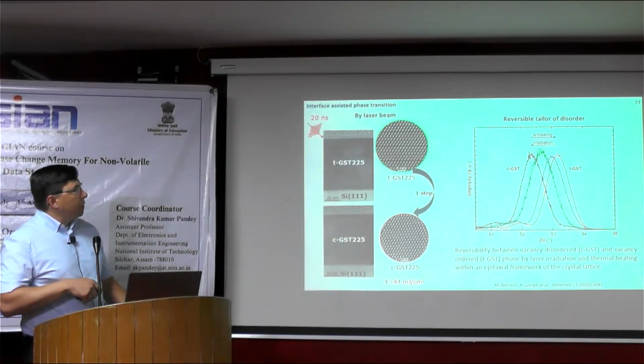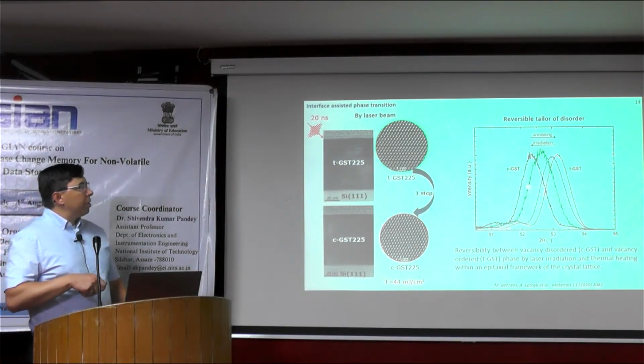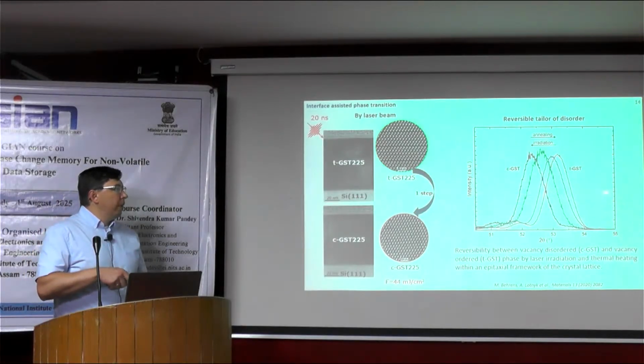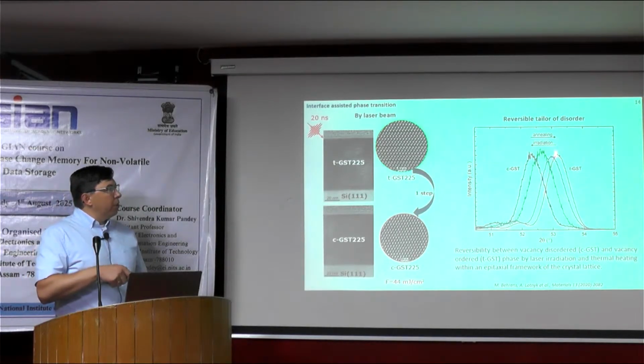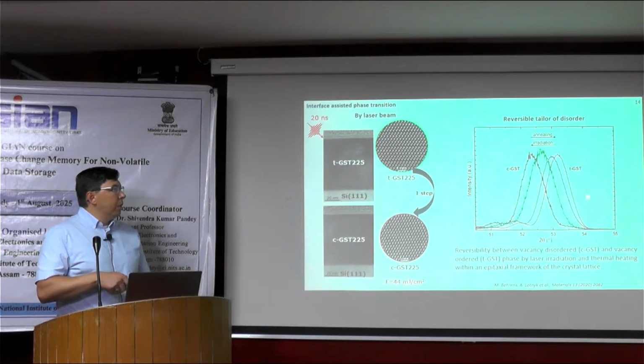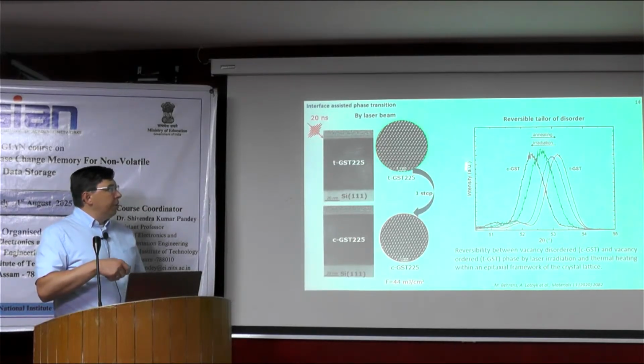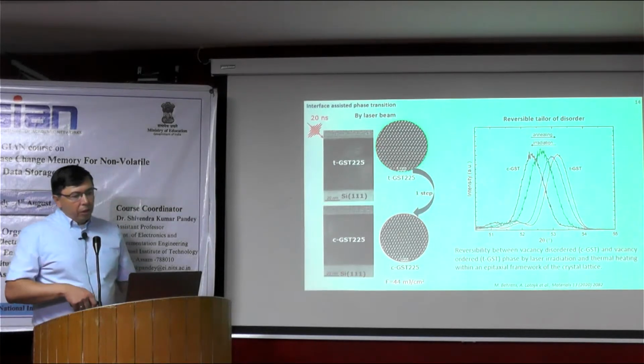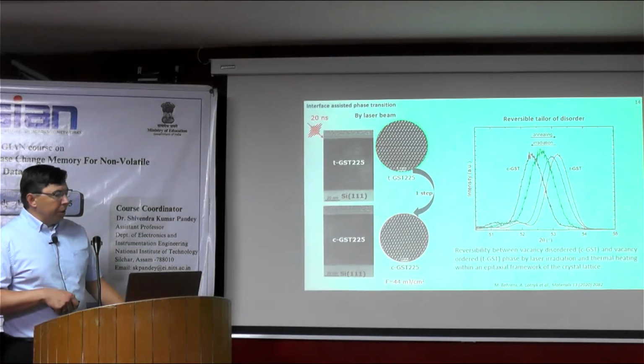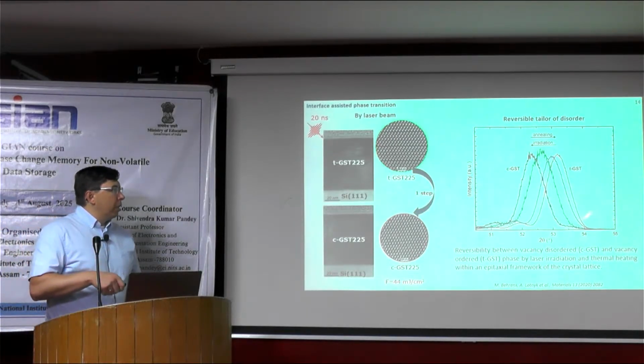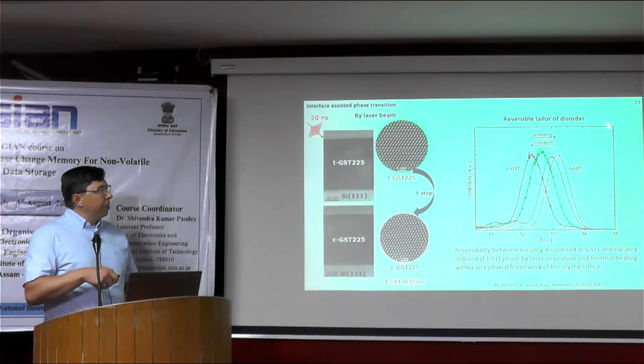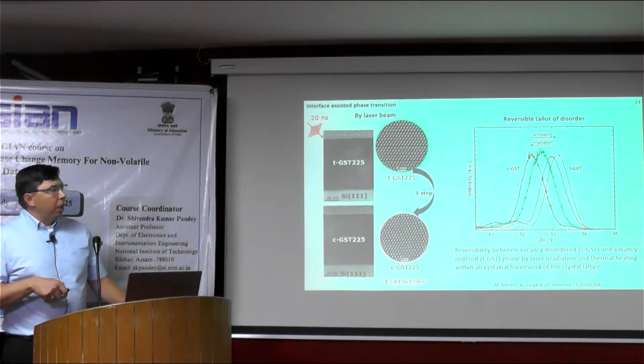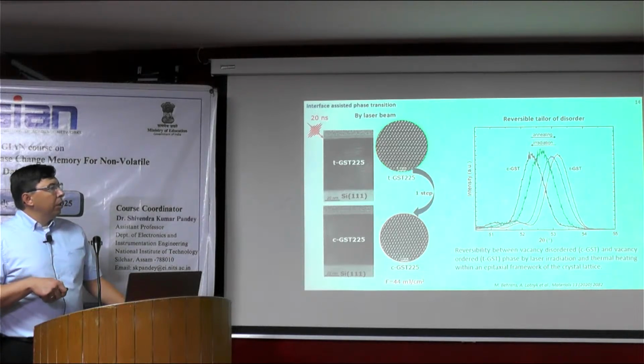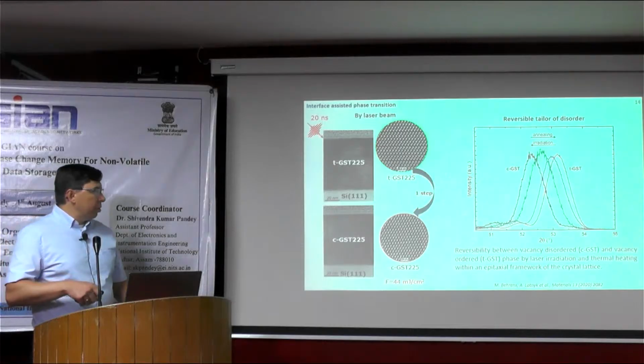If you want to go to the TGST phase, we can anneal or heat this CGST phase. Then we go through the different phase transition, like the vacancy ordered phase, and then TGST. And if you want to go back to the CGST, they use laser radiation. So it shows some possibility of phase tuning by using heating and laser irradiation. And if you can realize this in a device, we can maybe use it for optical data storage.